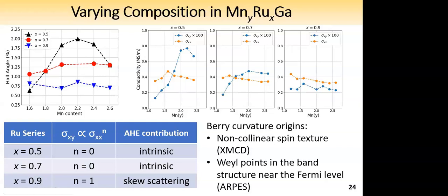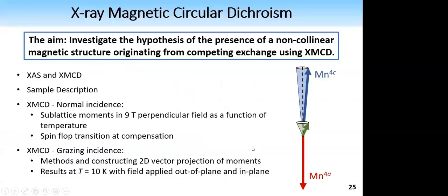So now that we believe we have this intrinsic contribution, the Berry phase curvature could originate from either non-collinear spin texture, which I will investigate by XMCD. It could also be due to Weyl points in the band structure near the Fermi level, which can be found in materials that break both time and space inversion symmetry. And that can be investigated using ARPES, but I'm going to focus in this work on the XMCD.